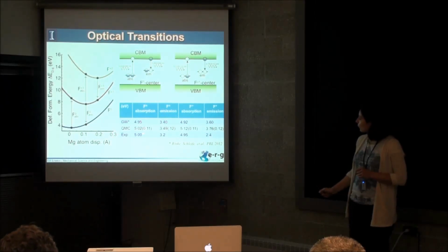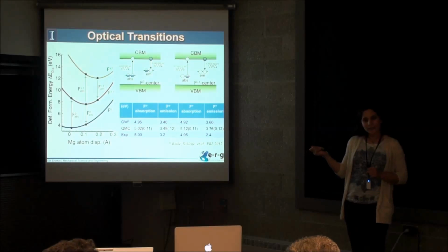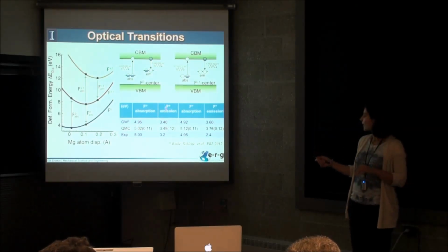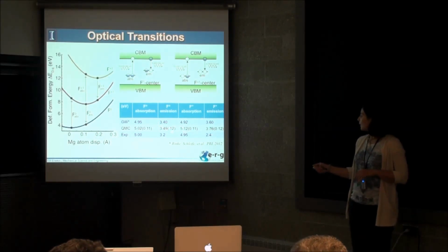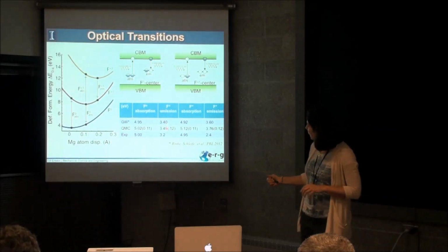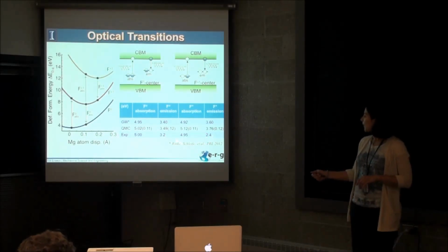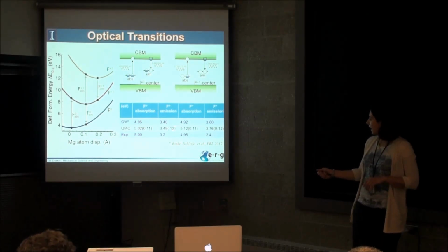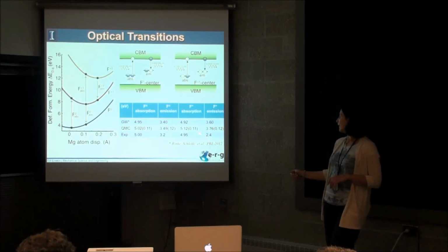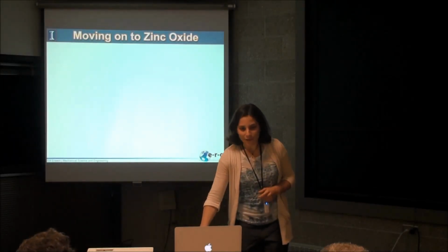They compare very well for absorption, not so well, I would say, for emission to experiment, but they actually compare really nicely to GW computed emission values. And actually this led us to think that this is an interesting situation where two different high accuracy techniques are getting similar results that are different from the experimental values as far as the emission is concerned. And this led us to think that, well, maybe it's worth going back and doing some spectroscopy on this system again and looking at these experimentally computed numbers one more time. If two independent high accuracy approaches are agreeing with each other so well, it might invite re-investigation of the experimental numbers. So that was our test case, actually, and I've run out of time, so I'm going to just cut to the chase.